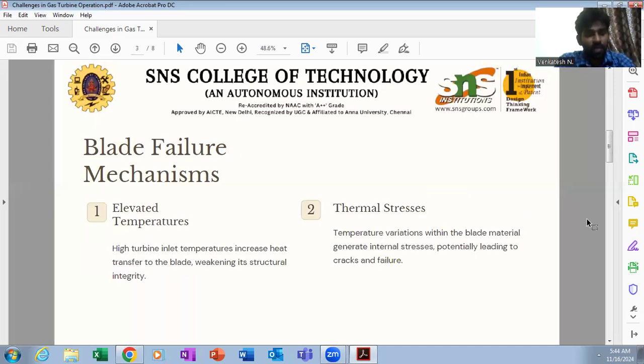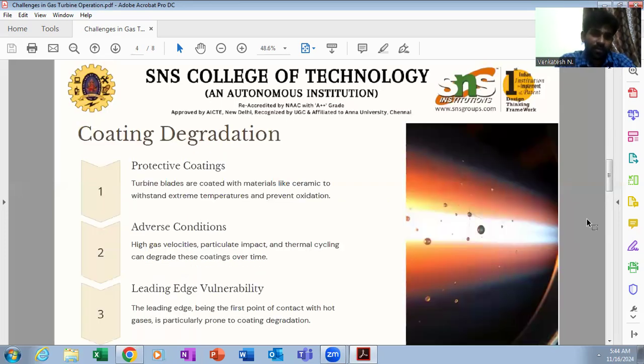The blade failure mechanism: elevated temperatures, meaning high turbine inlet temperatures, increase heat transfer to the blade, weakening its structural integrity. And thermal stresses: temperature variations within the blade material generate internal stresses, potentially leading to cracks and failure.